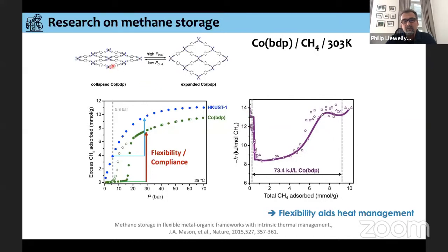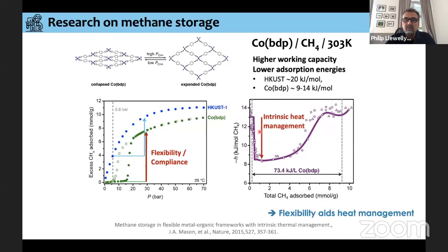So what this suggests is we're going from this form to this form. There's a certain amount of energy needed to reopen the pores. And this compensates the exothermic adsorption of our methane. And so the authors talk about an intrinsic heat management. What they suggest here is we get higher working capacities, but also lower adsorption energies, for example, compared with copper BTC and this material. And this may help in terms of processes.